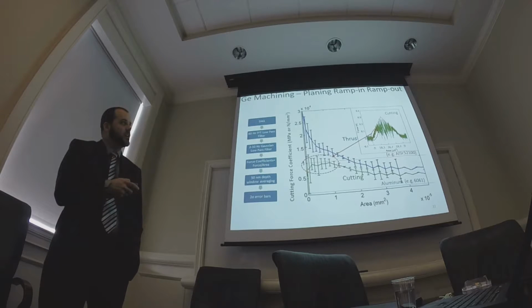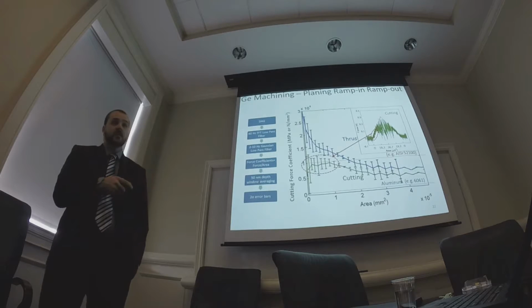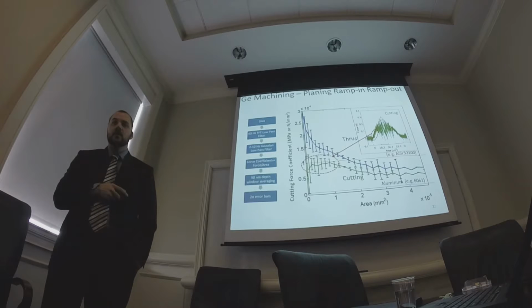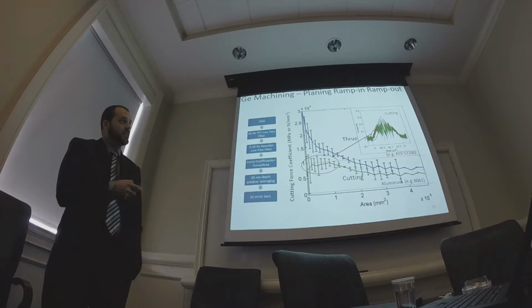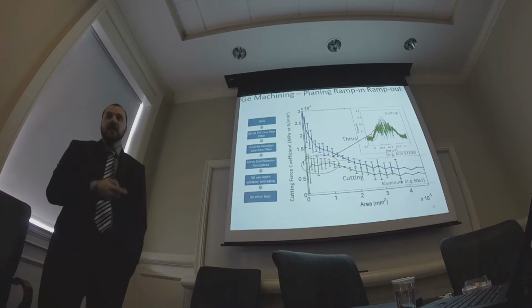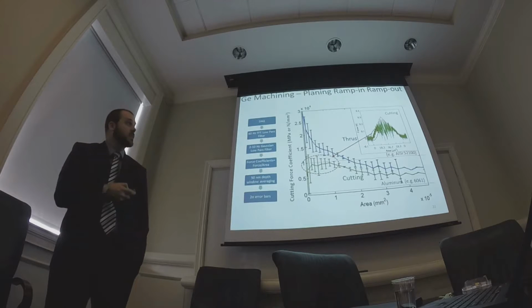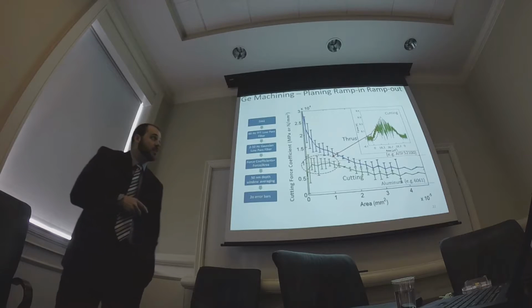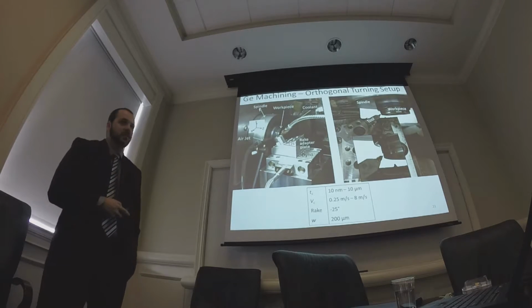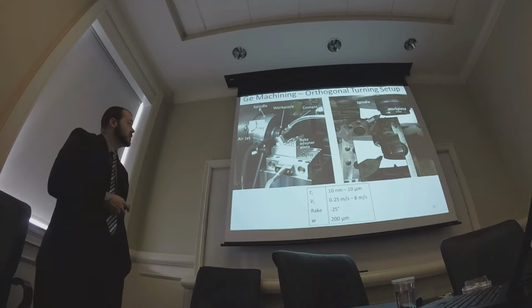If we assumed this cutting force coefficient through the entire test, we would have expected a straight line following this red line and back down. This is unfiltered, and none of the force exceeds where we'd expect that behavior to continue. When the tool hits a pit or breaks a chunk out, the force drops, then immediately after it may not fracture quite as bad and we get a spike back up. So we get fluctuation, but never exceeding what we'd expect from a purely ductile cut.